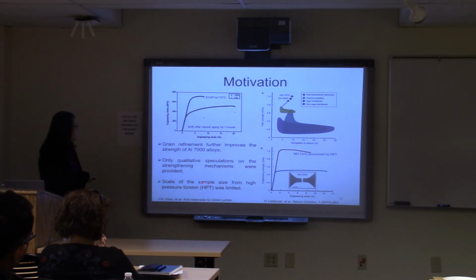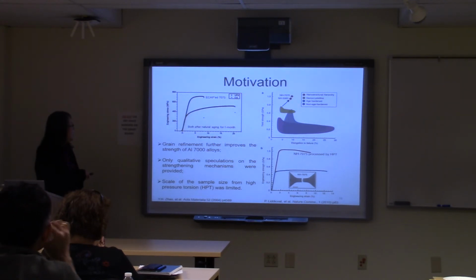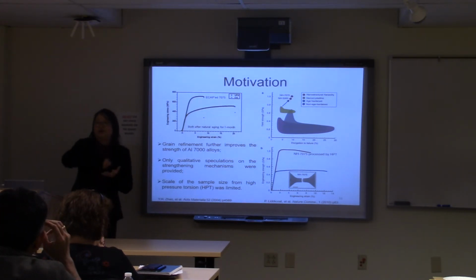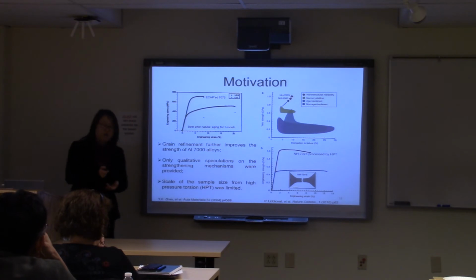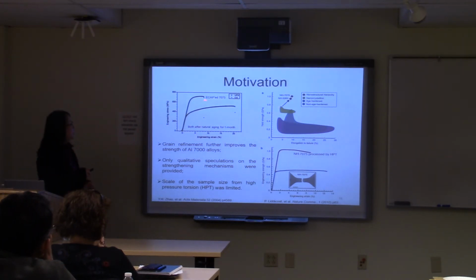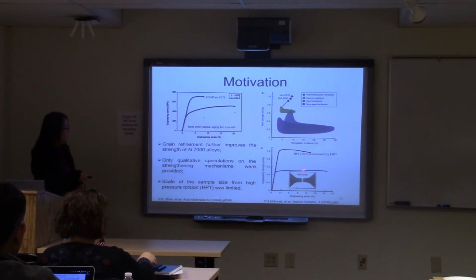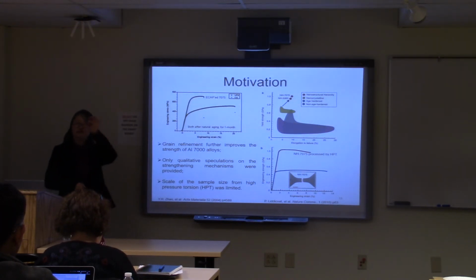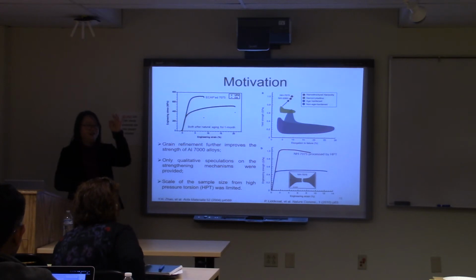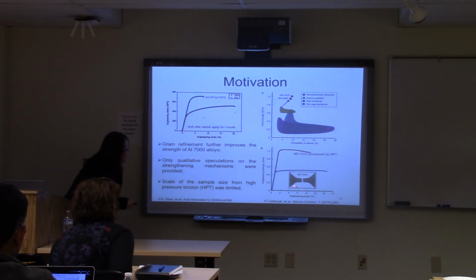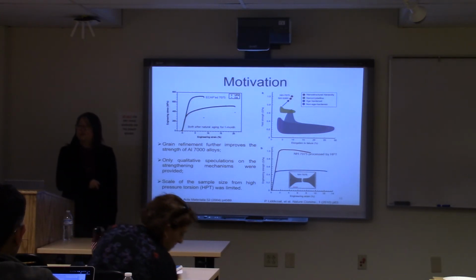There is some early work that applied different methods, like directly deforming the bulk material to reduce the grain size inside. And it's not surprising that you see an increase in strength compared to the traditional materials here. However, at that time, with the high pressure torsion method they used, they usually made the sample in this size, and the scale bar here is 1 millimeter.